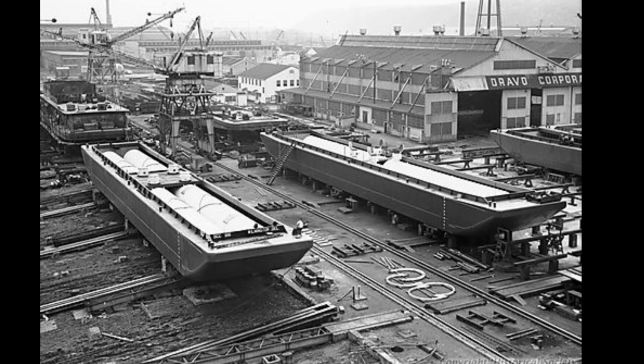After every series of welds, sections went into heat treatment ovens. These massive furnaces, each capable of holding a 30-foot steel assembly, heated the welded sections to 1100 degrees Fahrenheit and cooled them slowly. The process, called stress relief annealing, allowed the steel's internal structure to relax. Residual welding stresses that would normally be locked into the metal permanently were dissipated before the sections ever left the fabrication plant. Traditional shipyards didn't stress relieve anything.